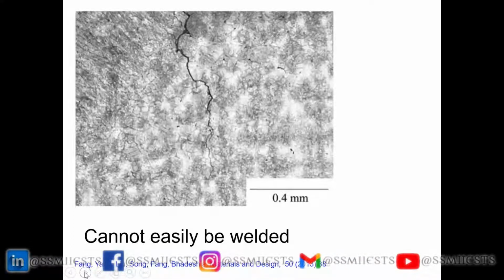Okay. So bainitic transformation is not going to do that. It's got to be weldable. That means we've got to go to lower carbon concentration, and the nanostructured bainite can only be produced at a sufficiently low temperature by adding lots of carbon. So we have to think differently. So if you go to the next slide,